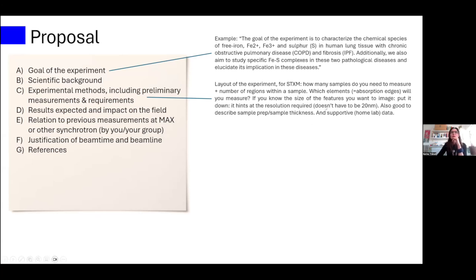And then if you have any information about how you prepare the sample, that would give us a hint of your sample thickness, which, as we showed, is very important depending on which edges you go for. So if you want to do carbon, tell me that you know that the sample has to be between 100 and 200 nanometers, and you can do it with your sample preparation. We have on site an ultramicrotome, with a trained person to operate it. So if you need sample cutting down to thinner thicknesses, that is available. And if you have something where you drop cast or so, that is also fine if you can have a bit of control over the thickness of the samples.